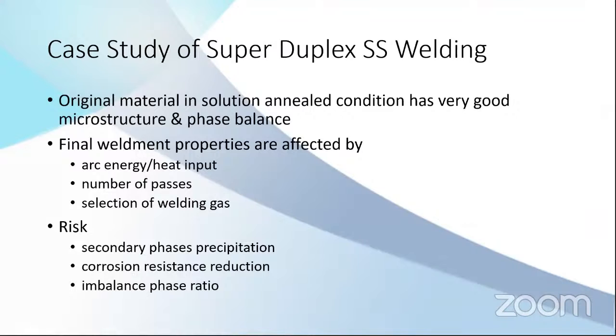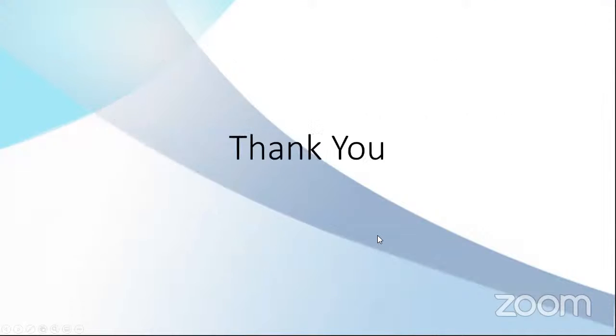So this is why weldment corrosion is important, because there are too many variables during welding. Heat input can be a variable, number of passes can be a variable, welding gas can be a variable. The parent metal composition can also be a variable, and that's why a corrosion test needs to be done before welding, during the PQR, to ensure that this kind of damage does not happen. What can happen? Secondary phase, corrosion resistance reduction, imbalanced phase, and we don't want that.